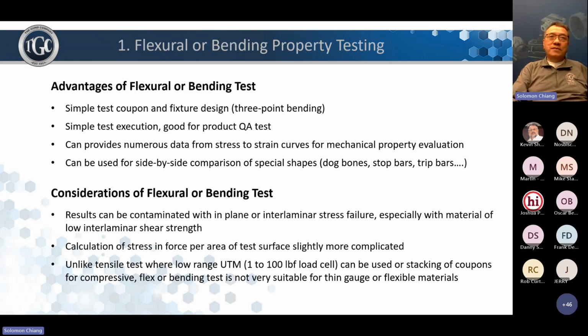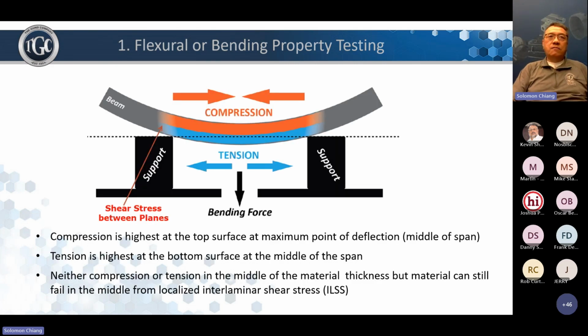Okay, flex seems to be simple, but in order to do it correctly and get the right number and arrive at the right conclusion, there are certain things that we need to watch out. The flex is essentially a 3-point bend. Sometimes people call it a 3-point bending test. The coupon or the specimen is supported on both ends, and we apply a force in the middle. And this explains what happened when you press it down.